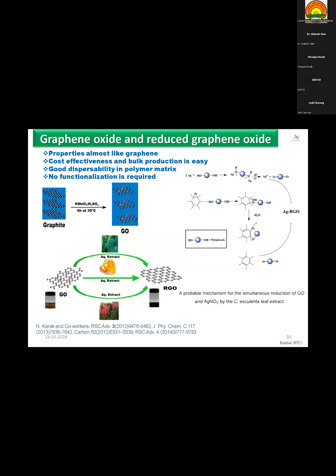Our major breakthrough was ultra-fast reduction of graphene oxide by using a bio-based system, whereas most conventional systems use chemical reduction processes. Graphene oxide is obtained from graphite by an oxidative process, the modified Hummers' method, and this graphene oxide can be reduced. As you know, graphene is very difficult to produce on a bulk scale, and hence it is very difficult to use industrially. Whereas, getting equivalent performance, reduced graphene oxide can be obtained on a bulk scale, and it can be used in industry, and hence its importance is very high.